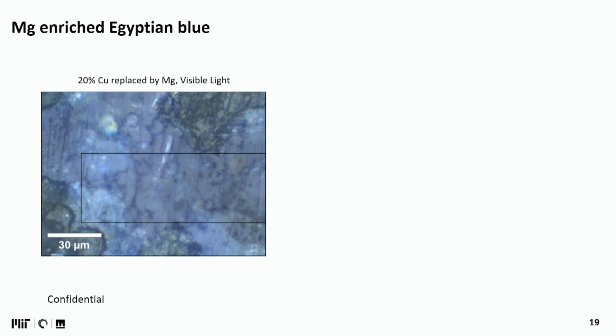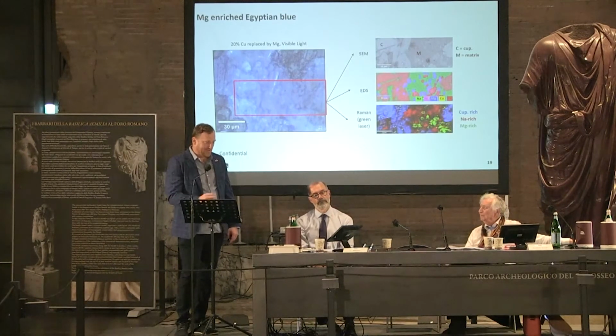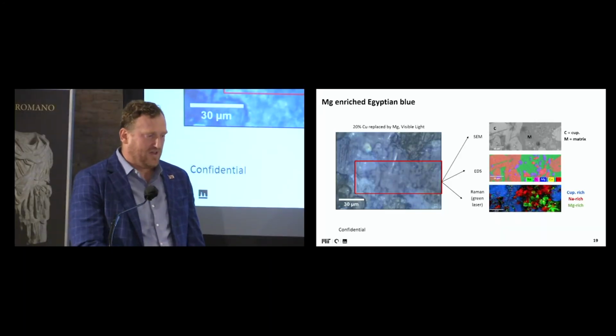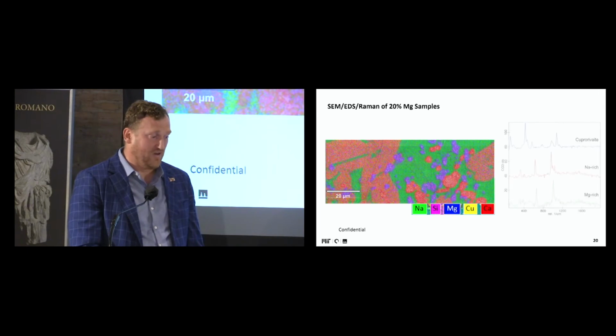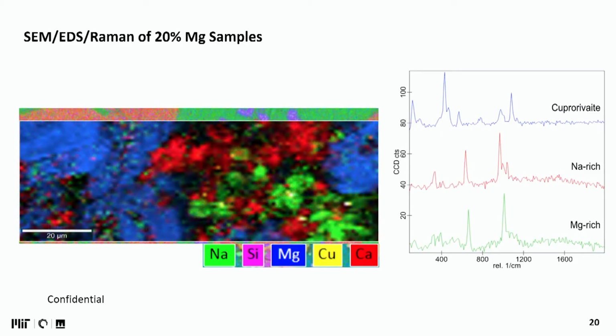Marco Nico would synthesize hundreds, thousands of these. So we picked some good ones and put them under the microscope. And indeed, you can correlate all this information into a series of images that are overlapped. So you have composition, Raman, and luminescence all together. And this allows you to answer questions such as, is magnesium going into the Egyptian blue or not?